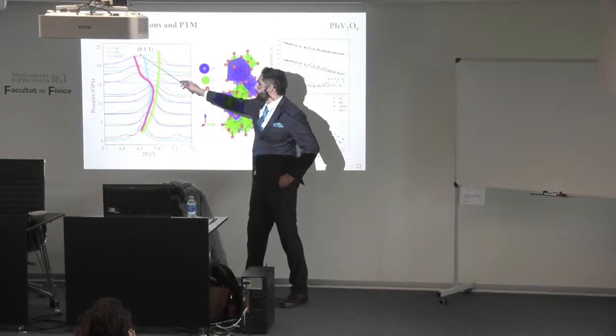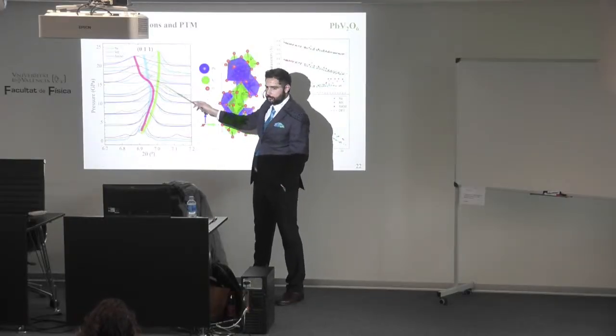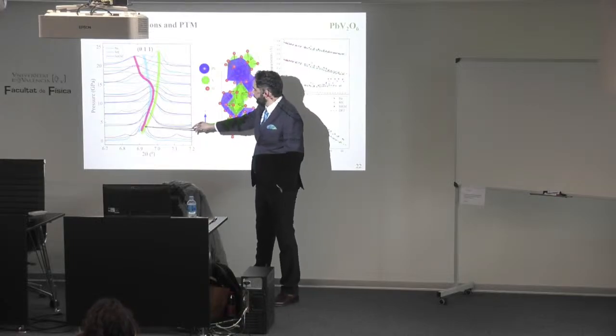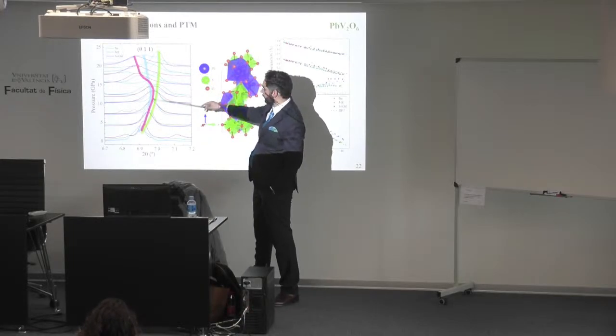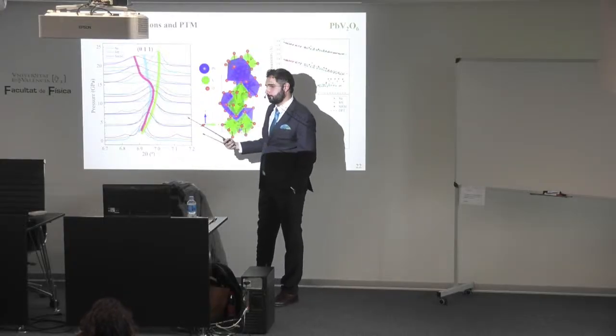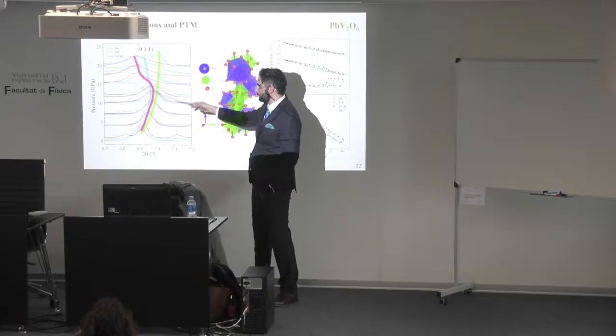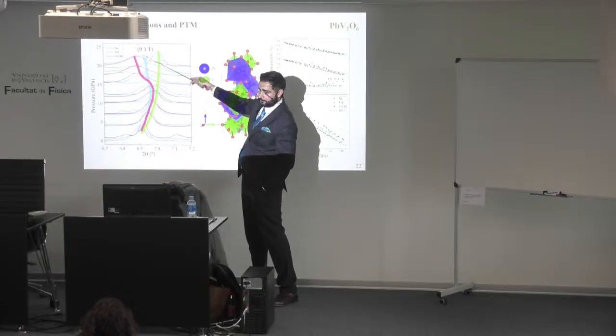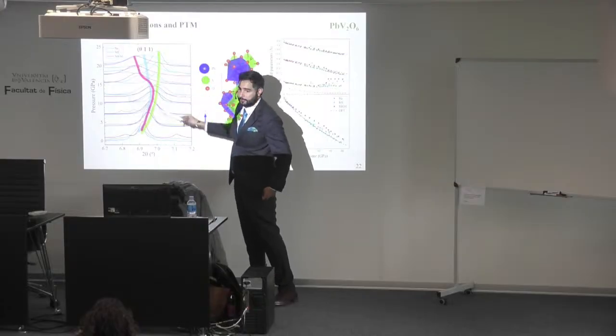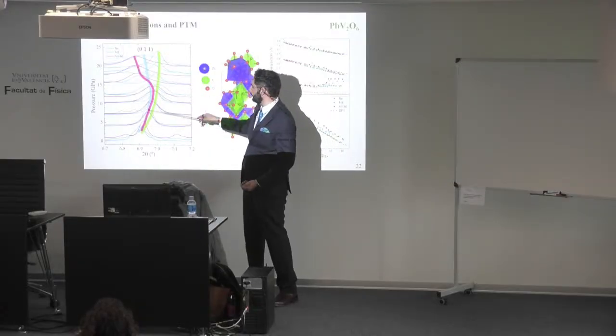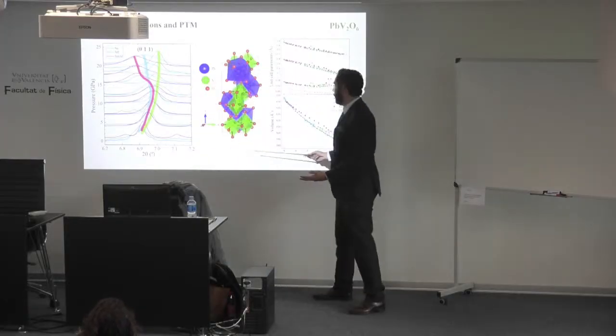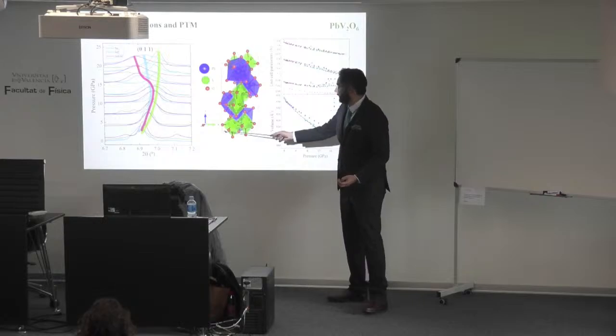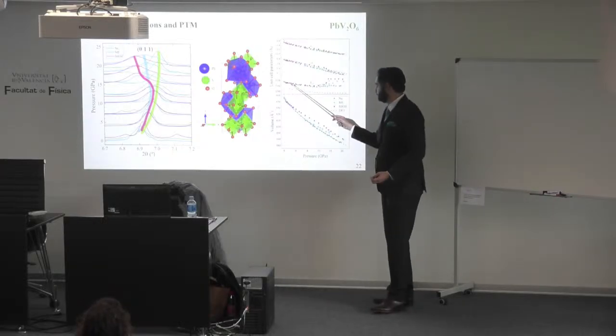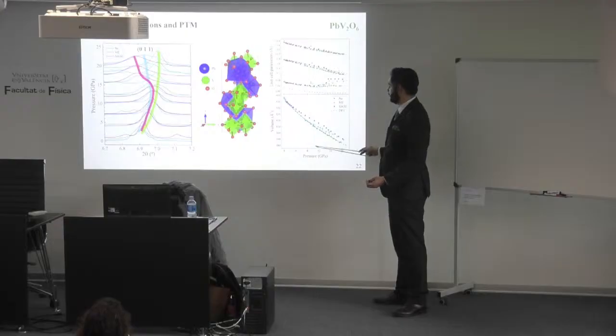When neon was used, for this (0 1 1) Miller index peak, it went to the right as expected and saturates here. When we used methanol-ethanol, that is not as hydrostatic in this pressure range, it went a little bit to the left. And then when using silicon oil, that is even less hydrostatic, it jumps to the left. Why is this happening? The B axis is the shortest one, and when reaching the hydrostatic limits of each pressure transmitting media, the conditions inside are no longer hydrostatic.